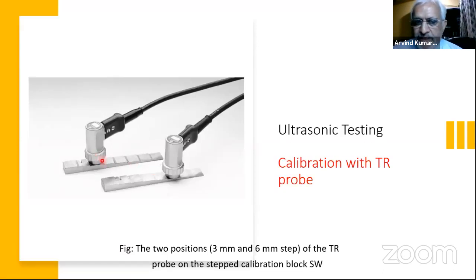You may require adjustments once or twice to make sure that 3 mm is showing me 3 and 6 is showing me 6. Once this happens, then you have a proper range of 6 mm or up to 10 mm. If you want a range of 20 mm, say 50 mm, then you have to use intermediate 2 thicknesses and do the calibration using those 2 thicknesses. If you do calibration using multiple echoes in this case, then your thickness variation would be there.